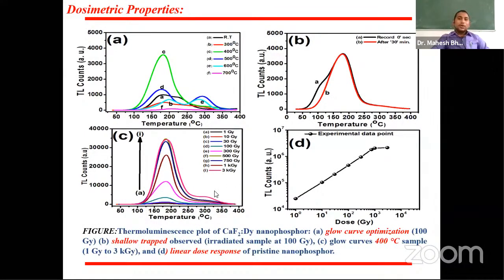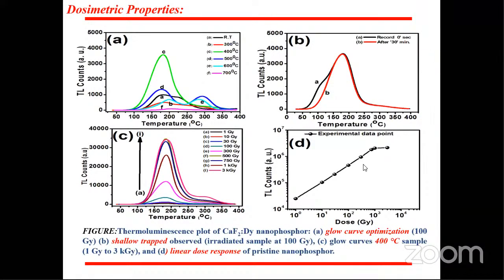After that we increased the dose. We bombarded gamma radiation onto the phosphor material and recorded the TL spectra, from 1 gray up to 750 gray. The dose response was linear, meaning this kind of material is useful in the range of 1 gray to 750 gray, and further it reaches the saturation level. So we chose this material for further analysis.